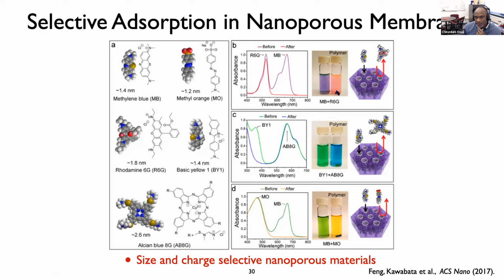So we did this, and we looked at the behavior or the properties of the system just in simple absorption measurements, right? So I hinted at the difficulty of making true membranes that one can test in the characteristic fashion, right, by pressure-driven flow. So what we did in this case is just test these membranes by absorptive uptake of molecular dyes. And what you can see here is very good selectivity based on size and charge in these membranes.